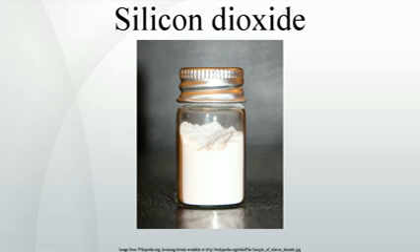Precipitated silica. Amorphous silica, silica gel, is produced by the acidification of solutions of sodium silicate. An initially formed gelatinous precipitate is then washed and then dehydrated to produce colorless microporous silica. Idealized equation involving a trisilicate and sulfuric acid is shown. Approximately 1 billion kilograms per year (1999) of silica was produced in this manner, mainly for use for polymer composites, tires and shoe soles.